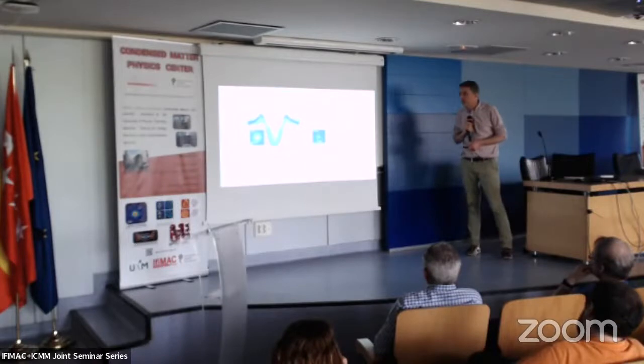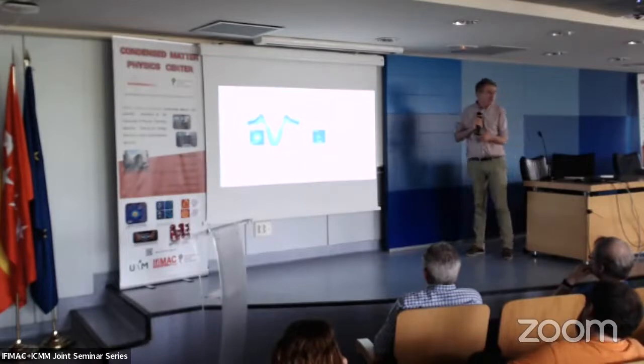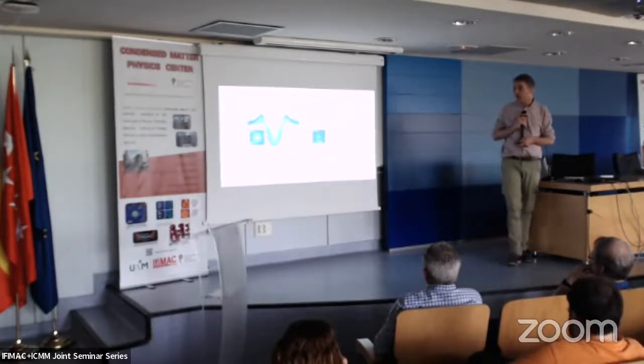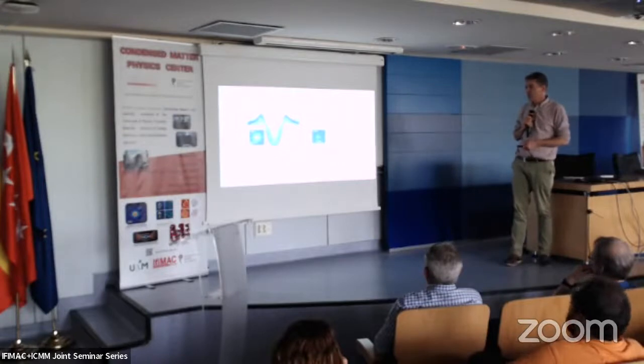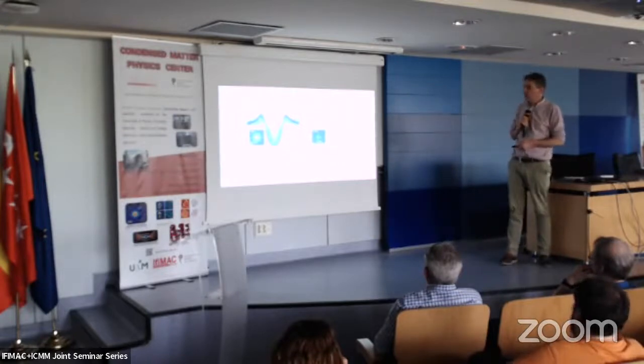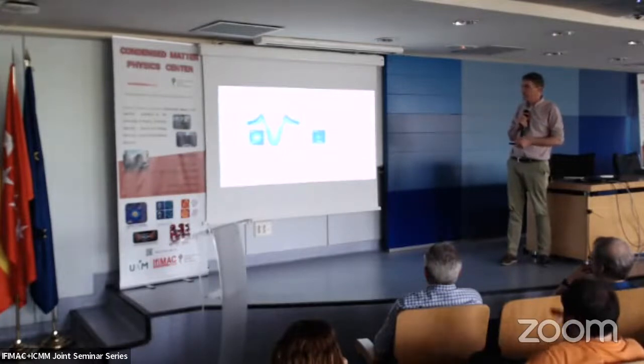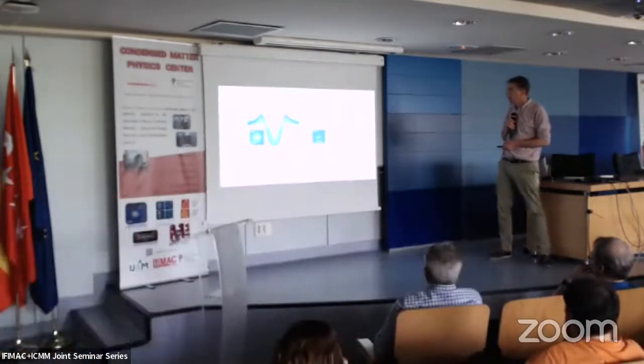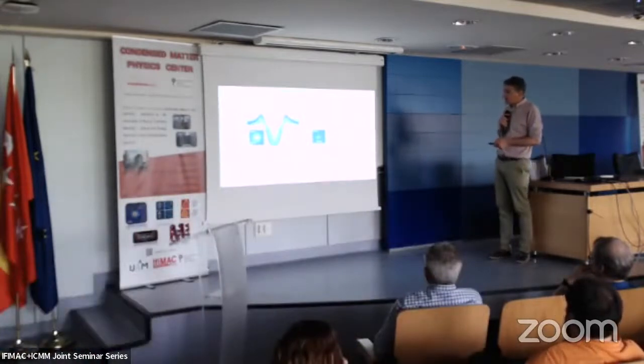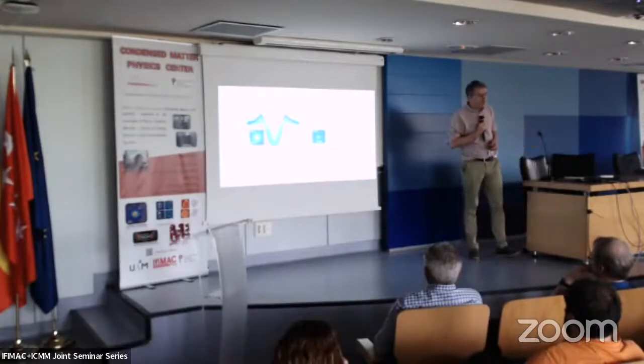Now, what happens if you have a vortex? Here you can see the length scales, which are really different. This bar is the same here and here. And here you can see that in the vortex there is this bunching of states which gives a peak at the Fermi level, and this peak evolves as a function of position. When you have a Shiba state, you also have an evolution, but it has electron-hole asymmetry, and the distance is given by the Fermi wavelength.